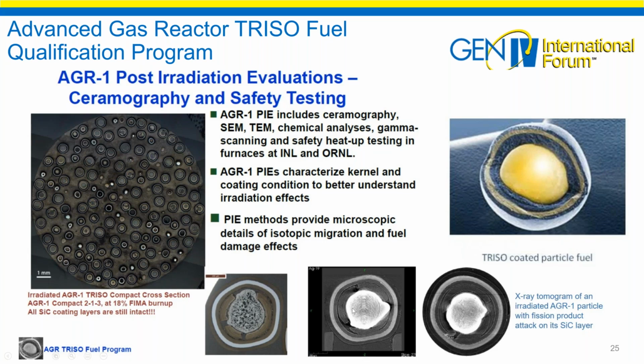And at Oak Ridge, we have an X-ray tomography capability where we basically do an X-ray through the particle. We actually can find where the breaches are, polish and cut so that we can look exactly where we want to look, and then do SEM, TEM, and then very high intensity TEM measurements as well. And for instance, you can see in this one, there's a little bit of palladium attack that we can actually see here on a silicon carbide layer. This is an AGR-1 particle. It didn't fail, but you could see the attack.